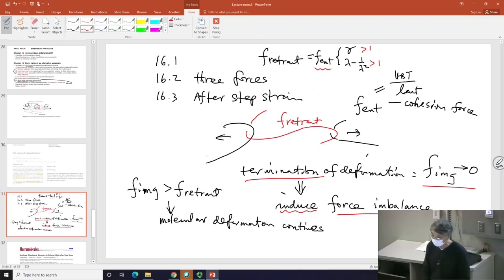Yeah. So that's when we envision that now the perplexed question is solved. The termination induces force imbalance because termination means you withdraw the intermolecular gripping force. So the retractive force just have to fight with this virtual force. This virtual force of only a magnitude of this much. So it can win as soon as you deform it enough. And that's why we see the non-quiescent relaxation and also the filament breaking up.